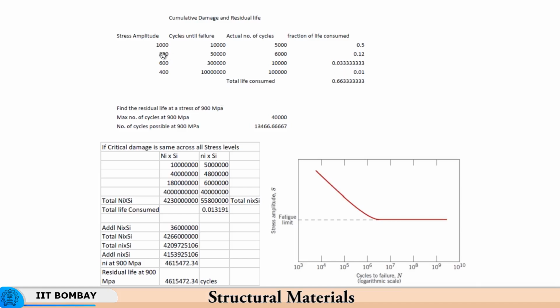So, for that what I do is that I have the stress amplitude and the actual number of cycles. So, not 5000 into 1000, I have the actual number of 5000 divided by cycles up to failure. So, cycles up to failure at 1000 MPa is 10,000. So, 5000 divided by 10,000 is 0.5. So, 50% of the total cumulative damage has already been done by this stress amplitude here. Then I switch over to 800 MPa as the stress and subject it to 6000 cycles, which means that 6000 divided by 50,000, because now at 800 MPa the cycles to failure are 50,000. So, naturally just 12% of the total fatigue damage has been introduced by 800 MPa and 6000 cycles.